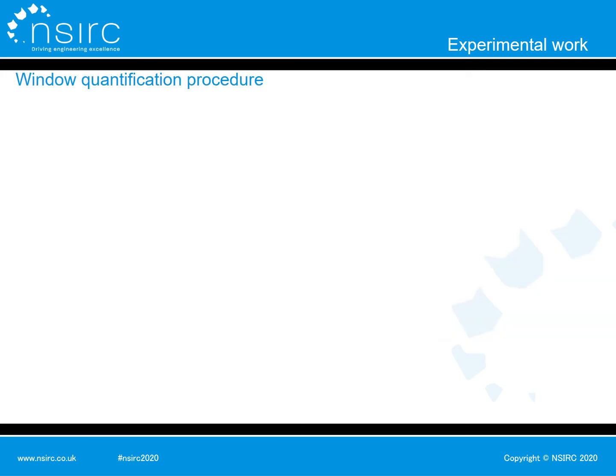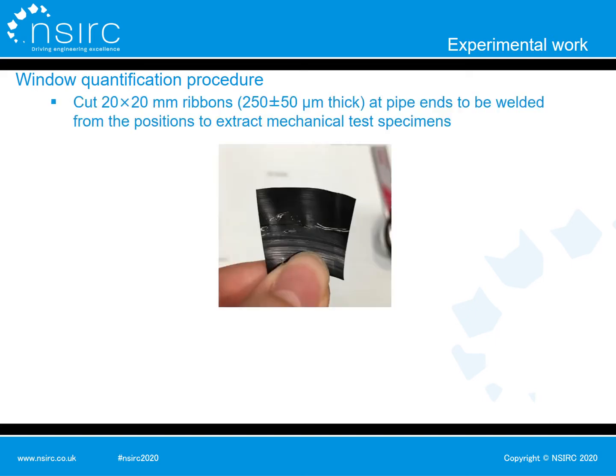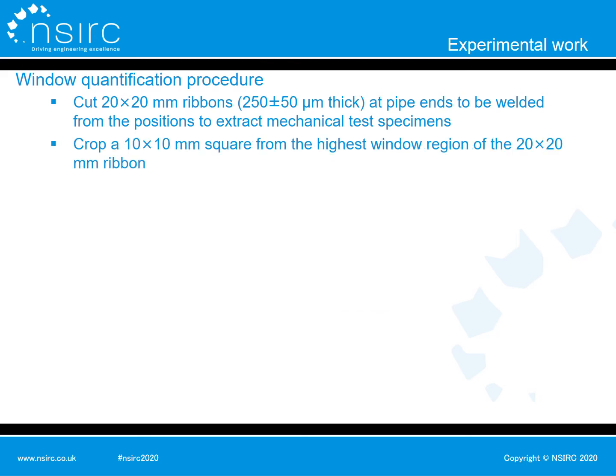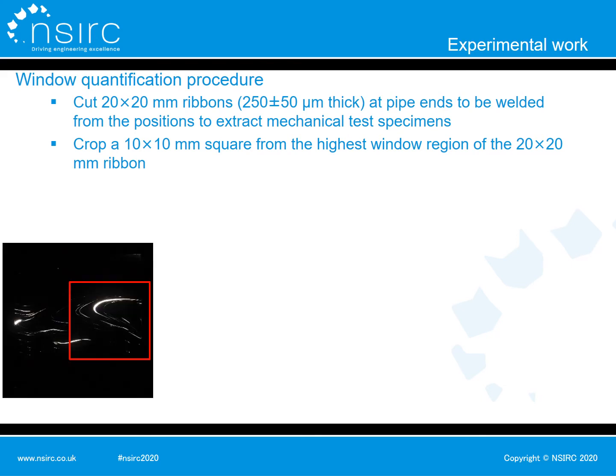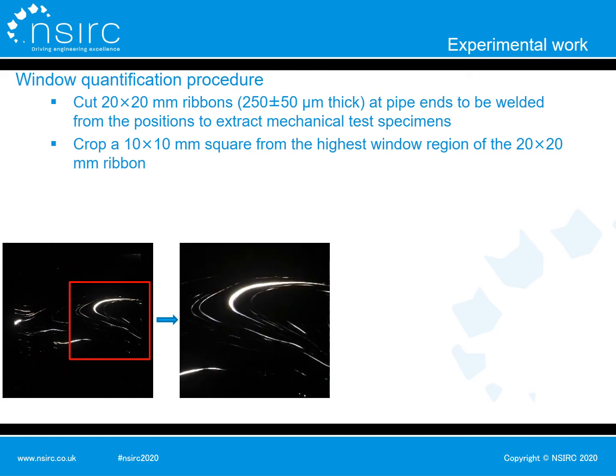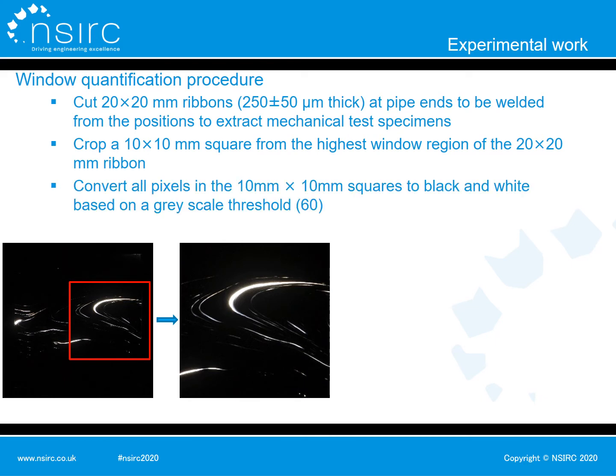To quantify windows in a test specimen, a 20 by 20 mm ribbon with thickness of 250 plus or minus 50 microns was cut at pipe ends to be welded from the positions to extract a specimen. Then, a 10 by 10 mm square was cropped from the highest window region of the 20 by 20 mm ribbon like this.